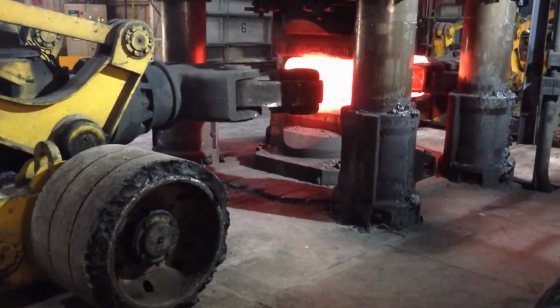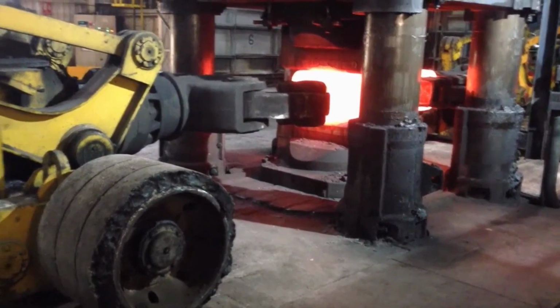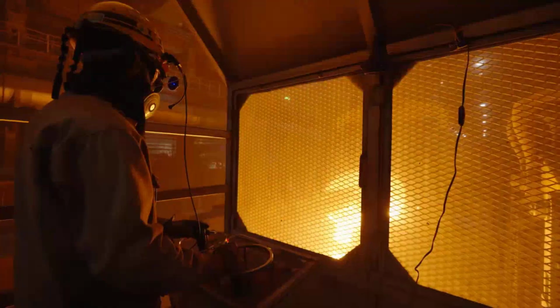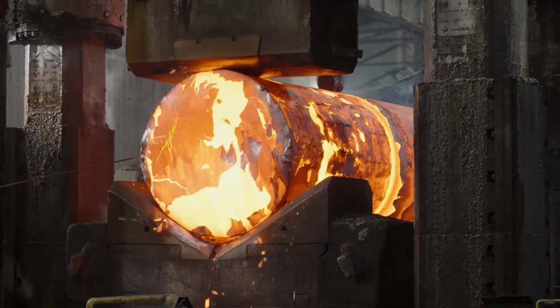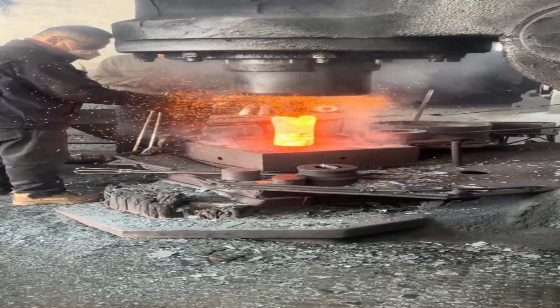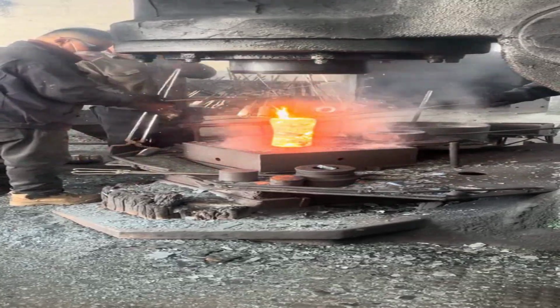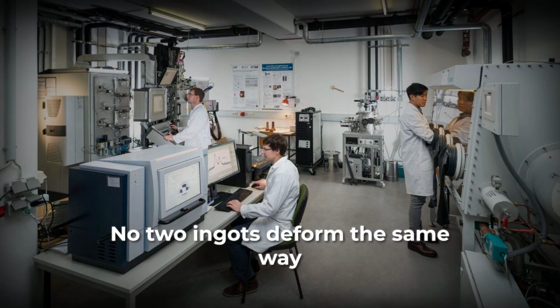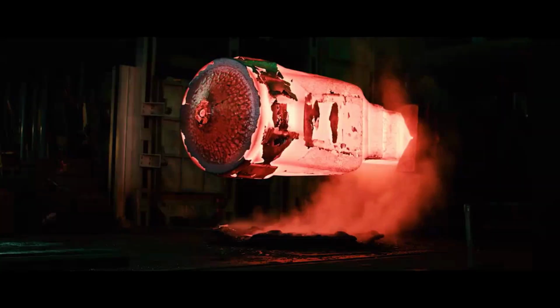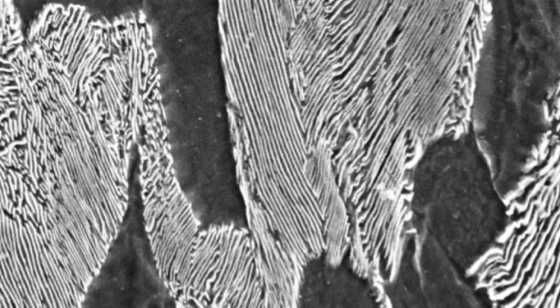What most people miss is that each ingot behaves differently, each one unique. Segregation patterns, the way different elements distribute themselves during solidification, vary with every casting. Research shows that deformation in these materials is not uniform because of the large size of the forgings, resulting in different grain sizes in different areas of the same piece.